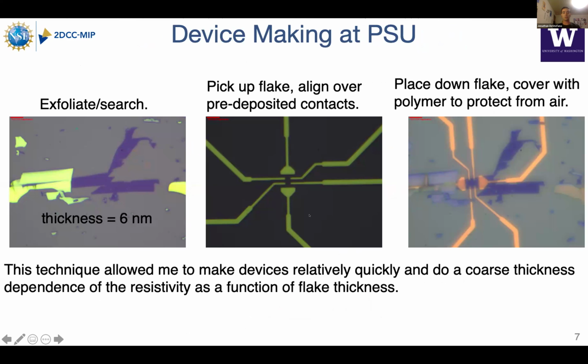June Zhu's group, who I worked in, were kind enough to provide me with some pre-deposited contacts that were comprised of gold and titanium. So if you pick up your flake using dry transfer techniques, you can align it using the transfer stage in the glove box over your pre-patterned contacts. And you can place down a flake and then cover it with a polymer to protect it from air when you remove it for actual measurements.